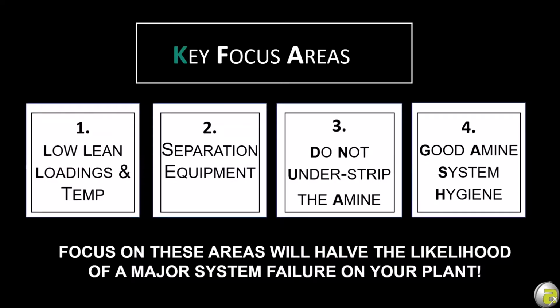Do not understrip the amine. Do not be afraid to regenerate the amine solution. Too much of the world is worried about overstripping the amine, causing corrosion, when in reality, the majority of the corrosion is caused by a failure to properly regenerate the solution. And finally, keep your amine system clean. That means good inlet separation, good carbon beds, good filtration, skimming anytime you can, and control contaminants coming in.